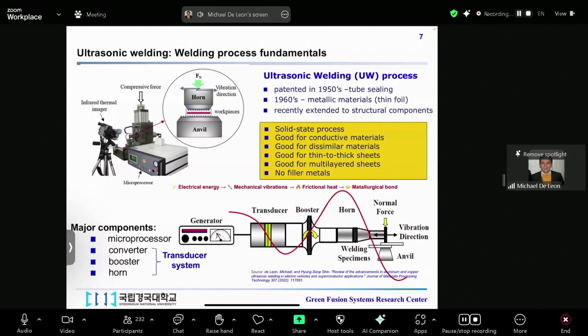Ultrasonic welding, or UW, is very capable of welding thin layers and dissimilar highly conductive materials like copper. It does not require any sealant, inert gas, or filler metals. And of course, it can avoid the typical metallurgical defects at the heat-affected zone, because technically it doesn't have any heat-affected zone, as the process is within the solid state.